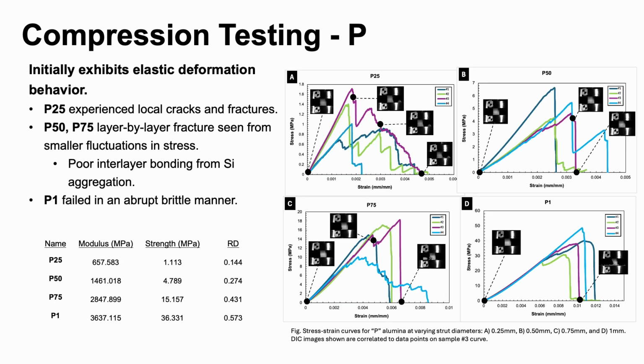So these are the results shown in the stress strain curves to the right for the P alumina lattice structures. From the stress strain curves, we see that all lattices showed elastic deformation in the beginning for the 94% alumina as well. For P25, the local cracks and fractures initiated at relatively small compressive loads, leading to stress fluctuations throughout the test. At P50 and P75, there were actually less fluctuations in stress, which were a result of struts being fractured locally layer by layer.